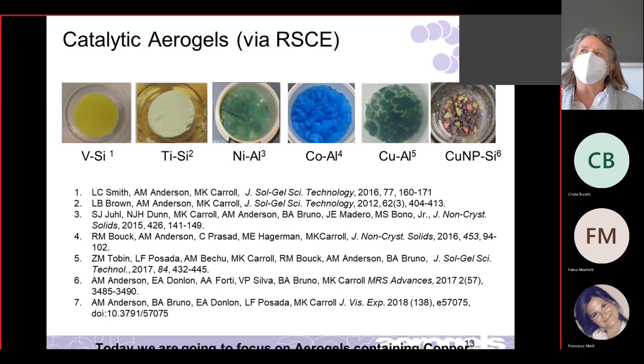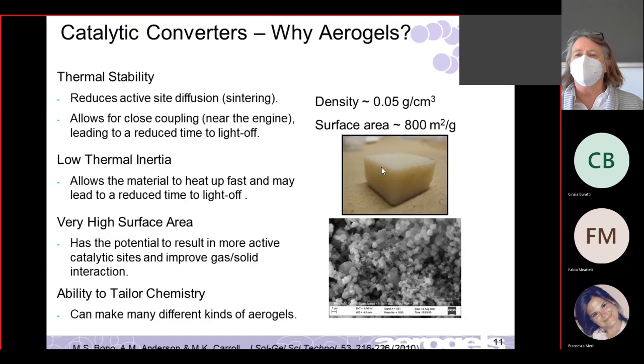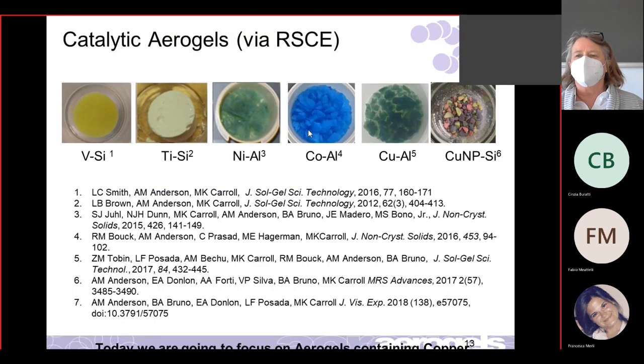So we switched then to doing things with alumina. So this picture is an alumina aerogel. And we switched over to doing some work with alumina, but alumina itself is not enough. So we dope the alumina with nickel, cobalt, copper. These are the ones that we've been working on. We've also done ceria and chromia. And then we've also gone back to silica. We did something with silica with adding copper nanoparticles. So these are some examples of the type we can make.